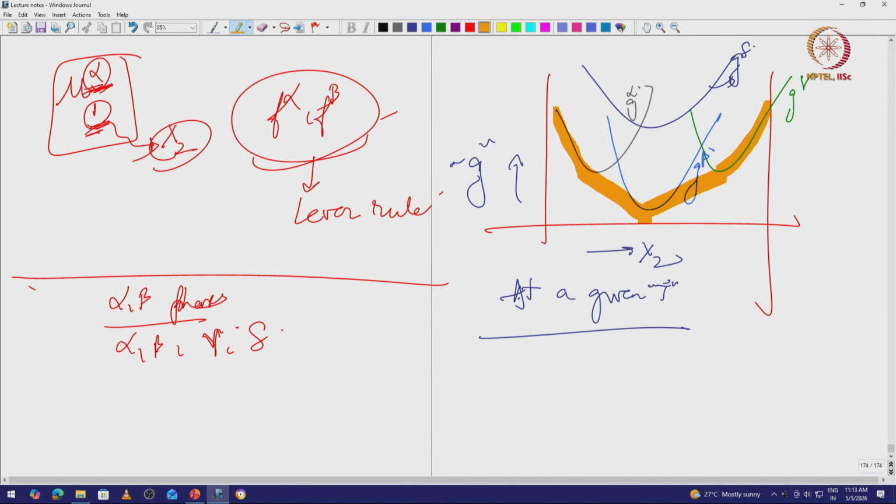So, until here I have an alpha phase that is stable. Until here I have alpha plus beta that wins globally. This is the global stability diagram, what this is called. From here to here, actually it is not alpha plus beta anymore, but it is beta plus gamma, right. So, here I have a phase boundary alpha plus beta.